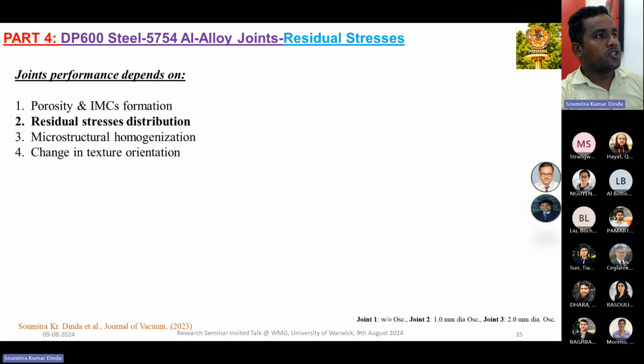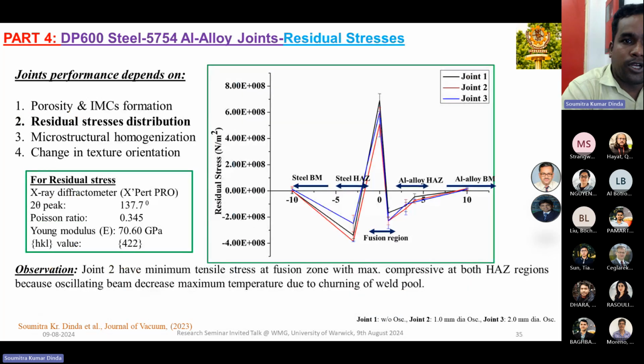Now, any joint performance mainly depends first on defect studies, that is the porosity and intermetallics. And the second thing is the residual stress distribution. Residual stress is also one type of defect formed due to the thermomechanical treatment or welding. And this is the typical graph we got. We got tensile stress at the fusion zone, and in both HAZ we got compressive stress because it's a negative value. Right? So if the tensile stress is less, that means good. Or if the compressive stress is more, that is the good one. Right? And this is the parameter.